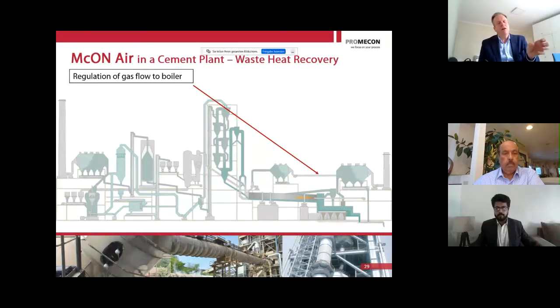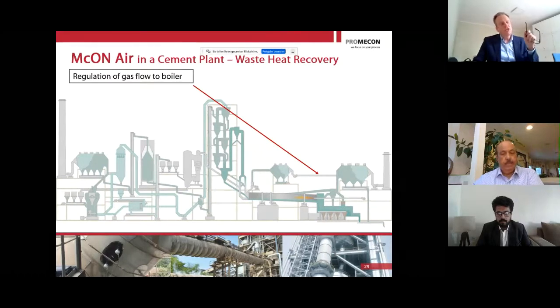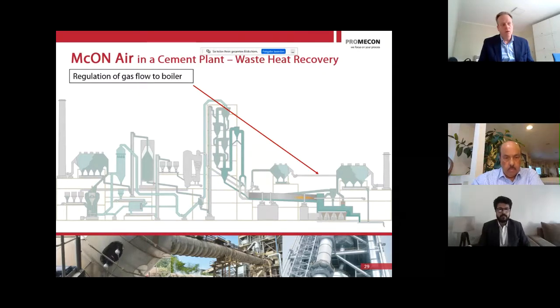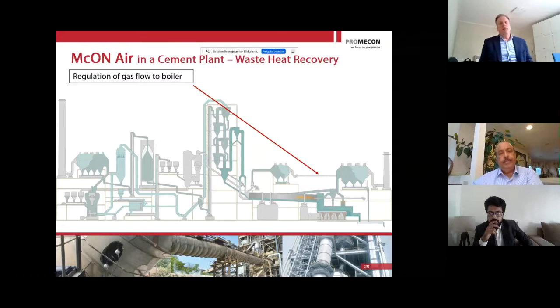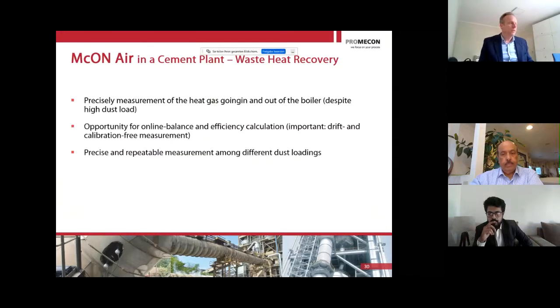Now, if you have different amounts of limestone falling into the clinker cooler, you have different air demands for the process of the rotary kiln. And that means that your air demand to the waste heat recovery is also changing. And for that, you need to have a good measurement to be able to control this flow. Otherwise, you will have the neutral point in your clinker cooler going back and forth all the time. Well, at the bottom line, it's again destabilizing the process, and you have more process noise than you want.